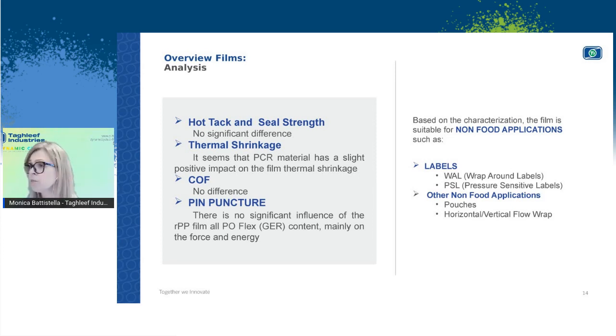When it comes to the performance, for instance, on the labeling machine, they were all successful. This film has been tested for wraparound applications by two brands, and it was successful in both cases. And even when it comes to pin puncture resistance, there was no significant influence of the presence of recycled content in the film itself. So we came to the conclusion that this type of film is absolutely suitable, of course not for food contact applications, but it can complement the need when it comes to the use of recycled material, and it can go in good combination with chemical recycled material. Chemical recycled material would be focused and dedicated to food applications, and this option may go for other applications where food compliance is not required.